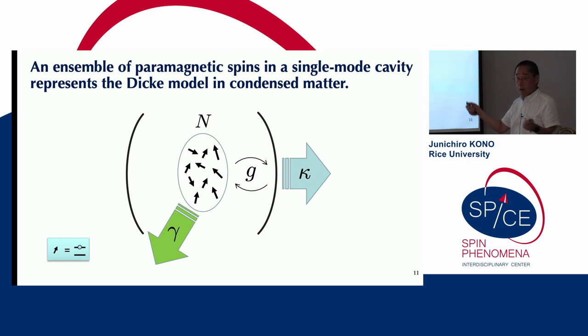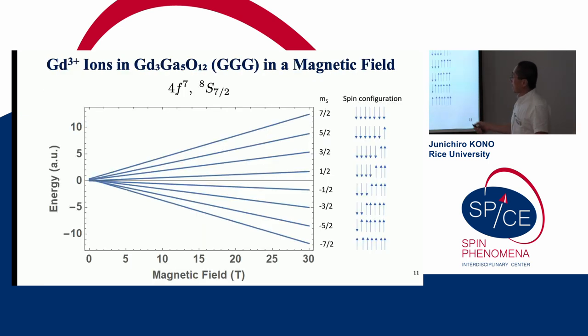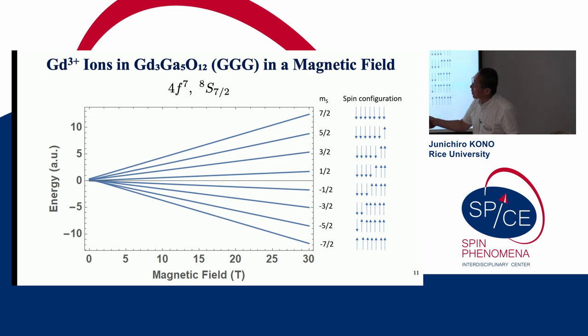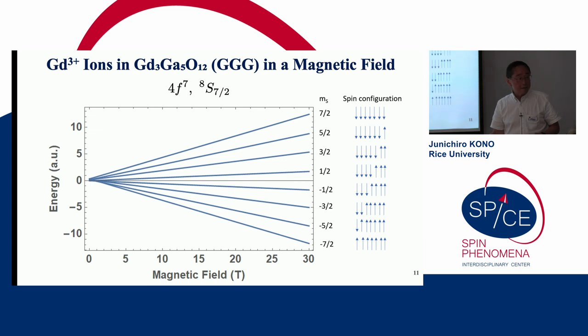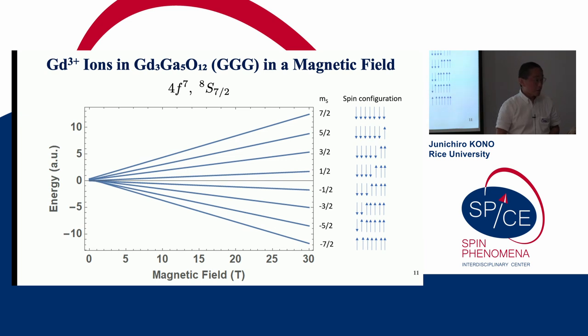That's why we're using paramagnets. The actual system we're using is something called GGG — gadolinium gallium garnet. We're interested in the spins of gadolinium 3+ ions. At low magnetic fields, there's some complication due to hyperfine splittings, spin-orbit coupling, and crystal fields. But at high fields like 20 Tesla or larger — we have a special tabletop magnet that allows us to do terahertz spectroscopy at such high magnetic fields — the Zeeman term in the Hamiltonian dominates.